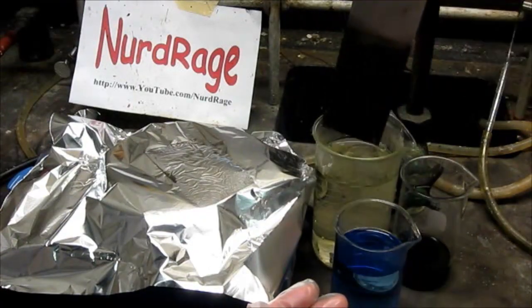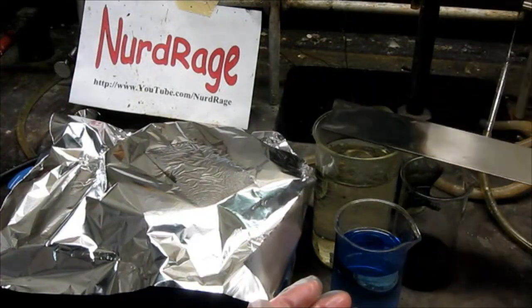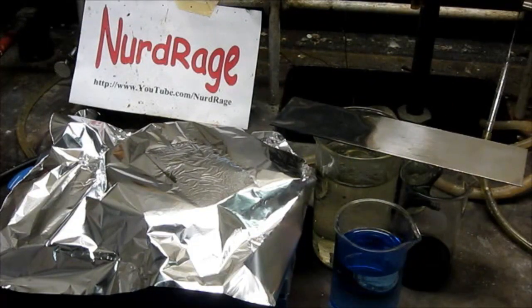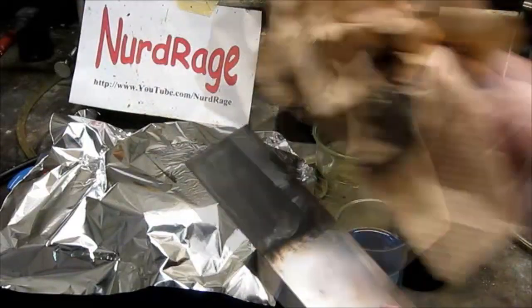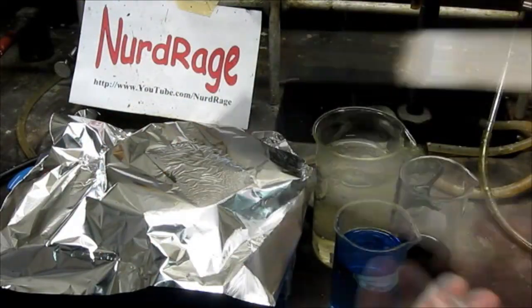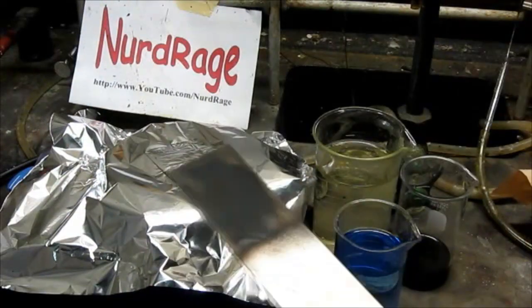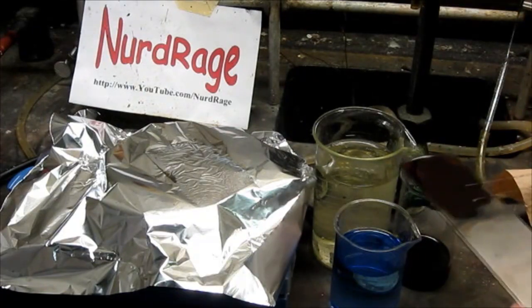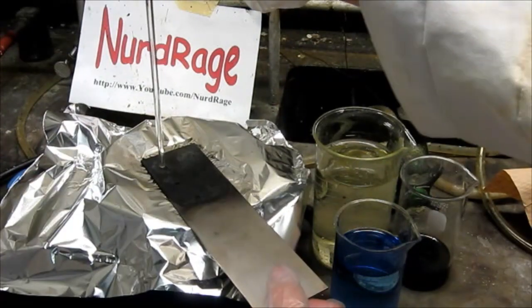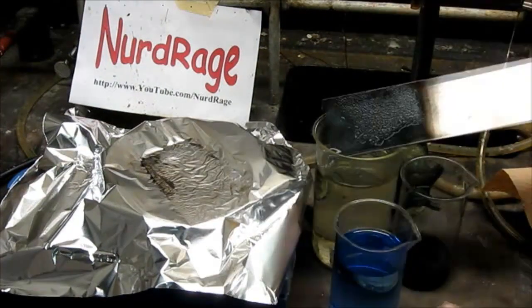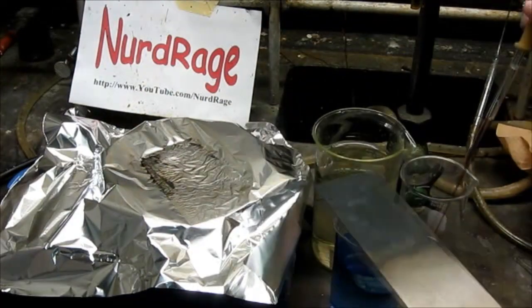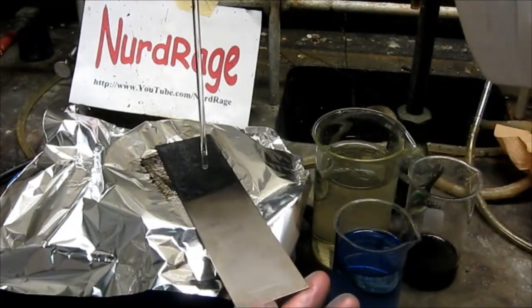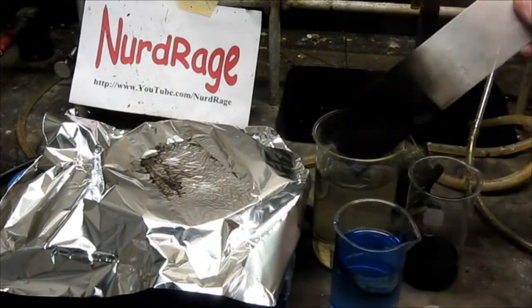Dip the electrode in cold water to cool it, and also to use the steam bubbling to blast off any loose cobalt oxides. Then wipe it down to remove anything that isn't strongly adhered to the surface. Towel it off and then apply another layer of cobalt nitrate and bake it again. Keep repeating the whole process as many times as you like, and remember to do both sides. I used about 4 layers or so.